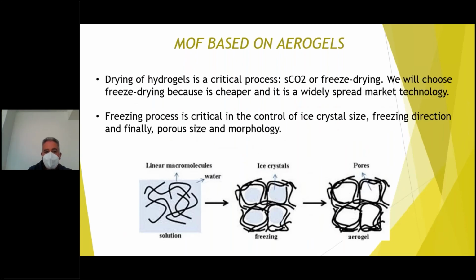process to make these aerogels is freeze drying. If we make the freeze drying process, literally a lyophilization process, we can control this nanometric structure. Of course, the freezing process is important, because if we freeze in an uncontrolled way, the size of the ice crystals is so big that probably the cavities are so big. It's important to control the temperature of the freezing process and the time, to control the ice crystal size, and finally the pore size and the morphology of the final aerogel. This kind of aerogel is really named a cryogel.